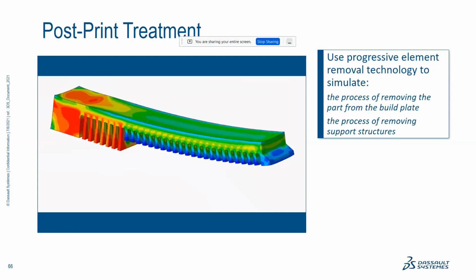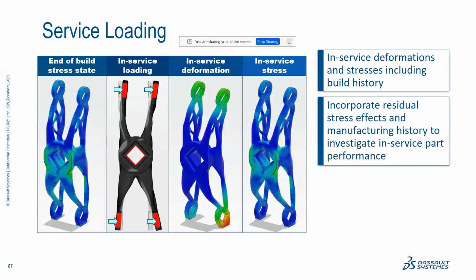And then once the part is printed, those ties will transfer the loads in terms of any distortion. But eventually they need to be removed by some sort of machining, which can be activated through the removal of these kinds of interfacial constraints. And any service loads can be estimated in terms of how it is performing. We can look at the end of the build stress state, any in-service loads, in-service deformation, and stresses.